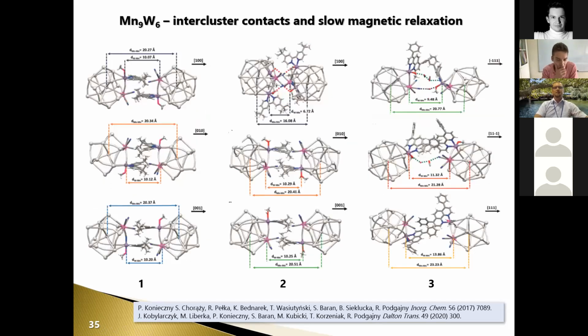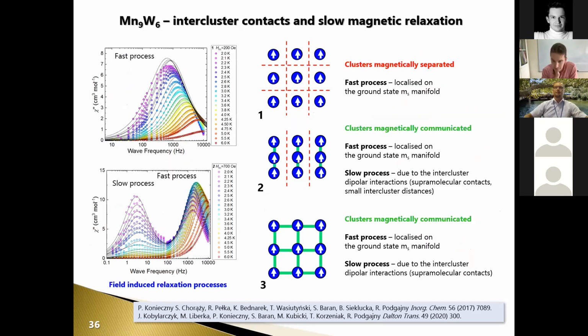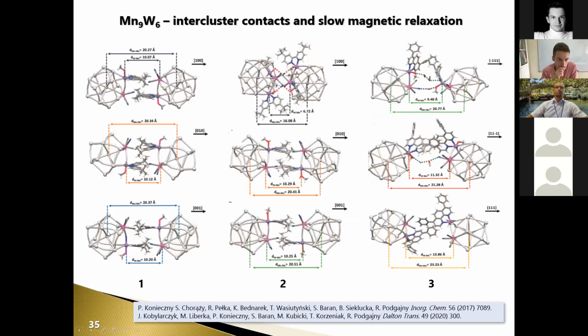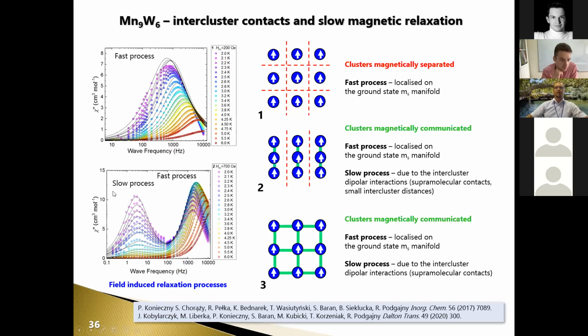What is the success of this study is that by using different ligands, we obtained various contacts between high spin clusters through hydrogen bonds or through pi-pi stacking or through just van der Waals interactions like here in this case. This is the case of a perfect isolation with quite large distance between clusters. We have only one fast process, while in other situations where there is notable molecular contact, I mean, through the non-covalent interactions, we see two processes, one slow and one fast process.